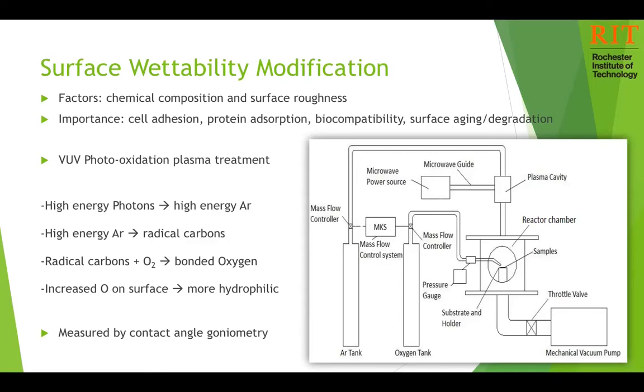One way to change the chemical composition of the surface is using a vacuum ultraviolet photooxidation plasma treatment. Here we have a simplified diagram of the process. High energy UV photons are generated from a light source at wavelengths which cause argon gas introduced into the sample chamber to become energized into a plasma state of matter. These high energy argon atoms then collide with the surface of the material to form radical carbons. Oxygen gas is then introduced into the sample chamber, reacting with the radical carbons and bonding to the surface as a result. As the oxygen content increases on the surface, the hydrophilicity will also increase.